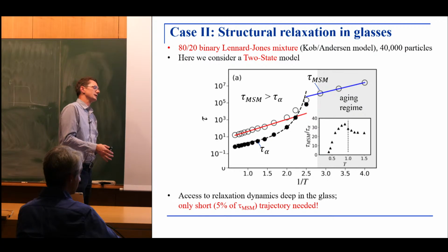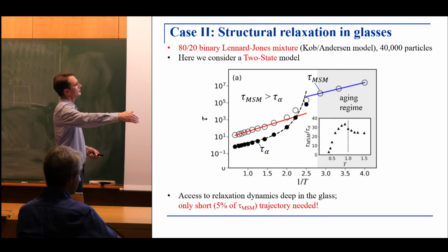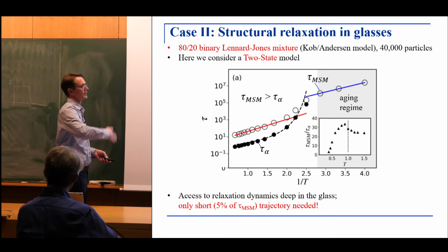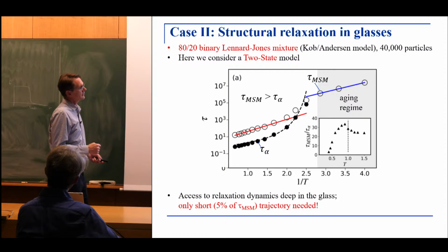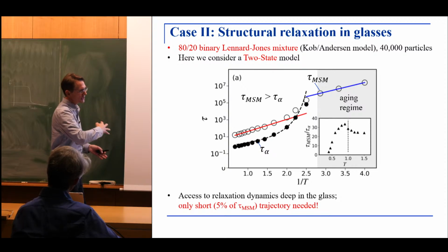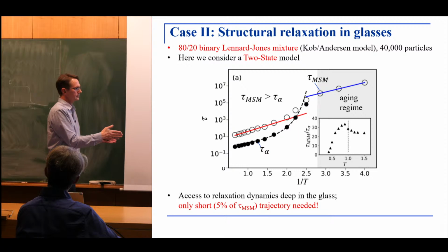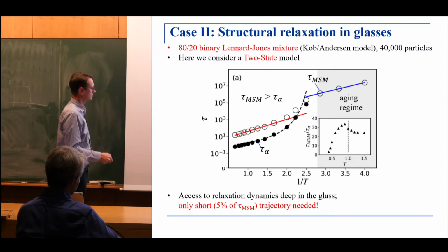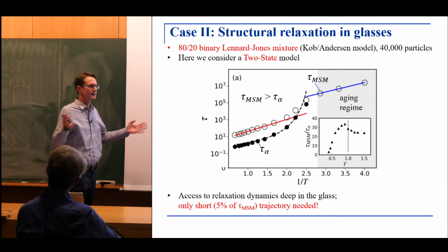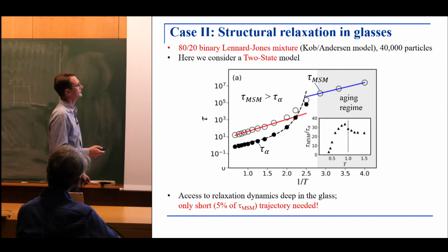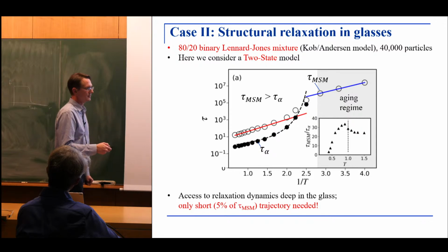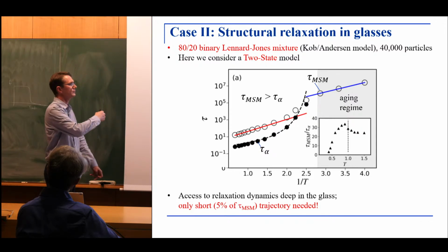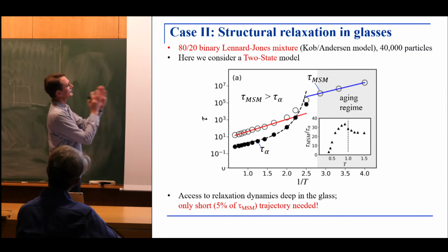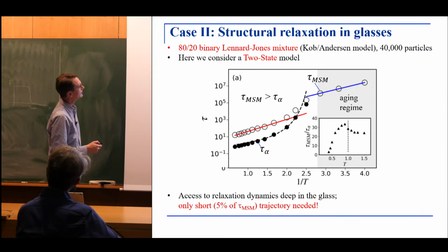Your model is becoming Markovian on a short time scale while it's aging. You should imagine that even though you're not in equilibrium, the aging dynamics is slow on the time scale you need to actually observe to make the measurement with the Markov state model. So that is the separation of time scales you need to have. Of course, if your system is changing so quickly, even during the time scale that you need to observe it, then you get some nonsensical result. But this is not the case here. Our cooling rate is slow enough so that the dynamics, although it is aging, is slow compared to the time we need to measure it. So I view this really as an instantaneous snapshot of the relaxation time.